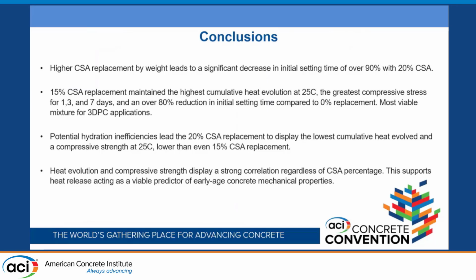And so, just to summarize, we have our conclusions being that at higher CSA replacement by weight, we see a significant decrease in initial setting time, up to 90% with the 20% CSA replacement. And then at 15% CSA, which is the more exciting one, you can maintain a high cumulative heat evolution at 25 degrees Celsius, the highest of all of our specimens tested. You can also see that it has the greatest compressive stress at 1, 3, and 7 days.